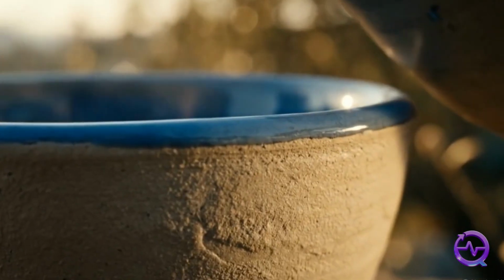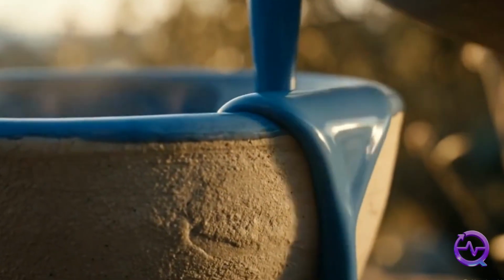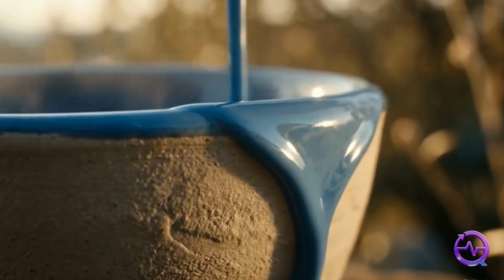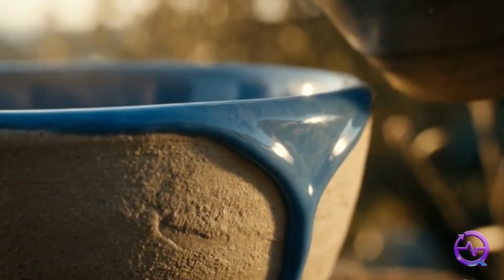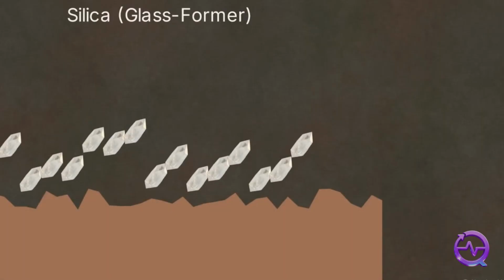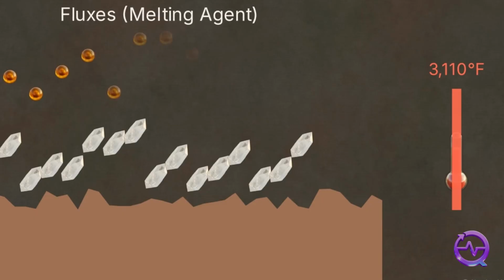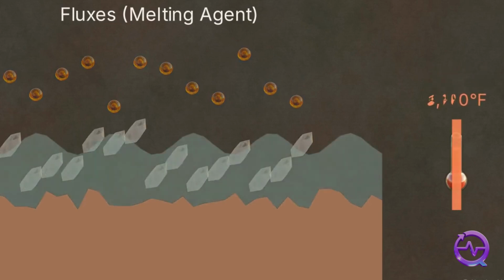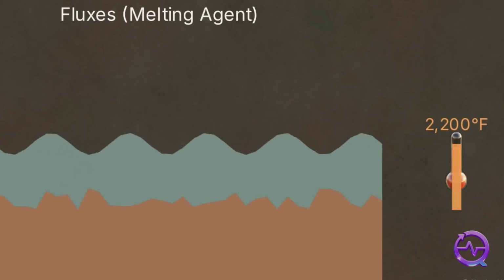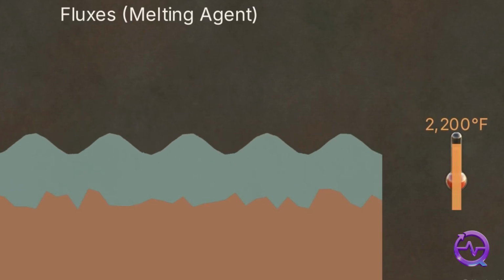Firing also enables the chemistry of glaze, a layer of liquid glass that fuses to the ceramic surface to make it waterproof and food-safe. Ceramicists achieve this by balancing three primary components. First is silica, the glass former. On its own, silica requires temperatures exceeding 3,000 degrees to melt, which is impractical for most kilns. To manage this, fluxes like calcium or sodium are added.